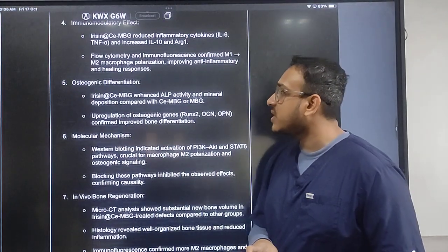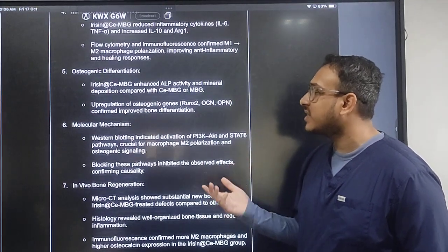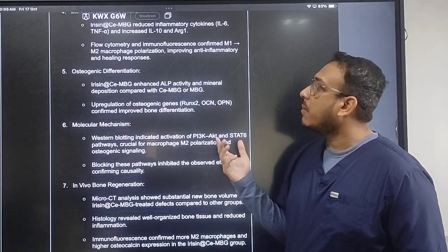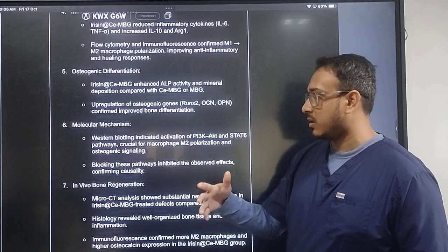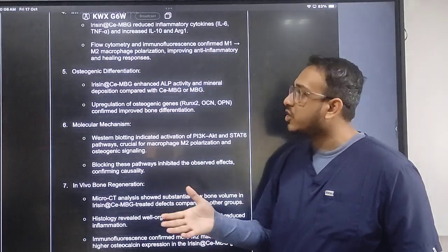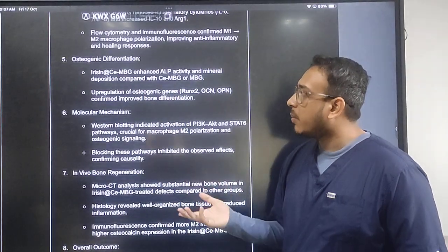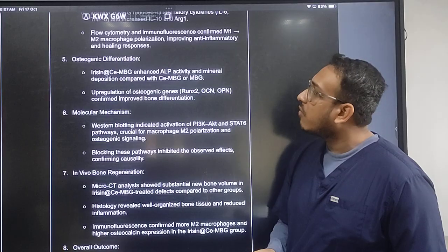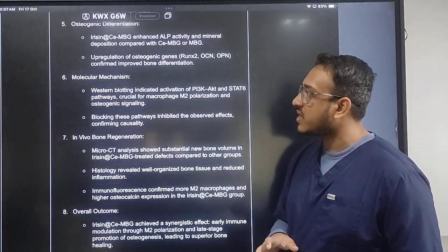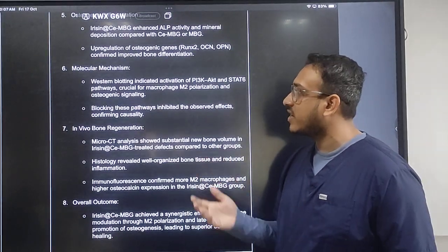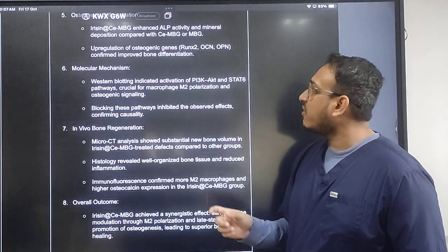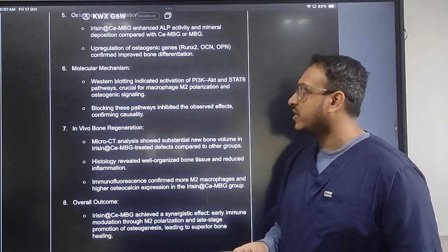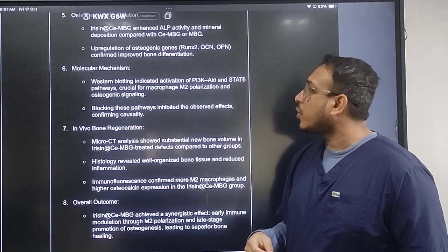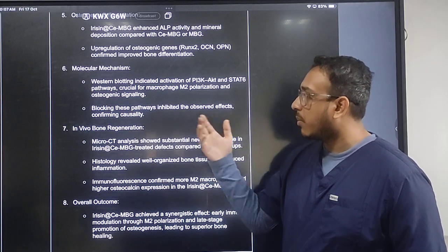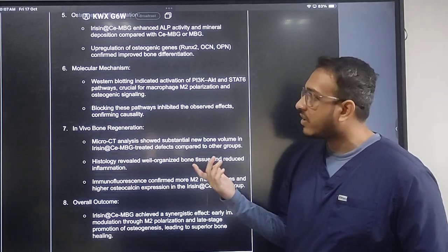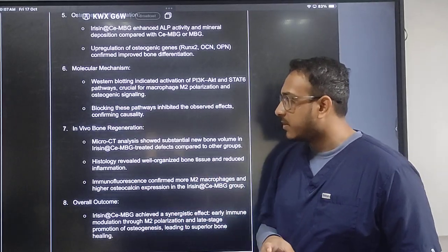The osteogenic differentiation: the material showed enhanced ALP activity and mineral deposition compared with the material's individual parts. The upregulation of osteogenic genes was confirmed, indicating improved bone differentiation. For the molecular mechanism, Western blotting indicated activation of pathways which are crucial for M2 polarization and osteogenic signaling. Blocking these pathways inhibited the observed effects, confirming the causality.